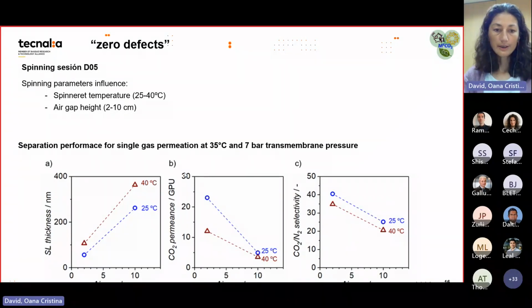Because of a higher selective layer thickness, the carbon dioxide permeance is lower. But what was surprising was that in this case, the selectivity was also lower. So in other words, at a higher air gap and a higher temperature, we achieve a higher thickness of the selective layer, but also more defects. And this is without any PDMS coating. This is because there is some humidity absorption from the environment, because we were not using any dry nitrogen flow in the air gap. But it's good that at very low air gaps, we did achieve very good selectivities, and we also have higher carbon dioxide permeance.